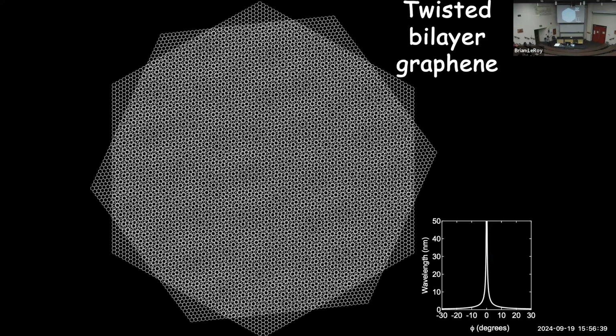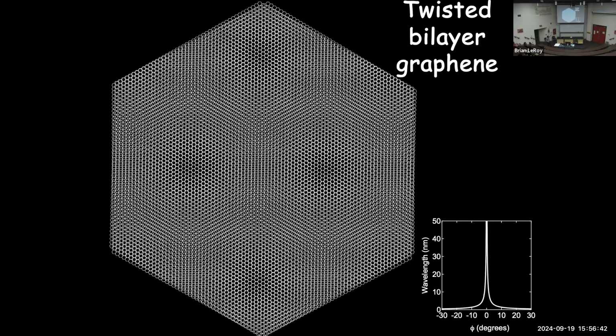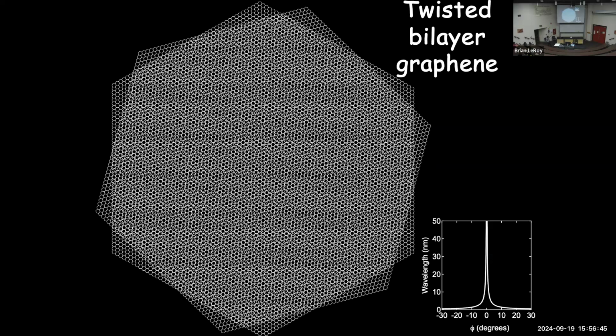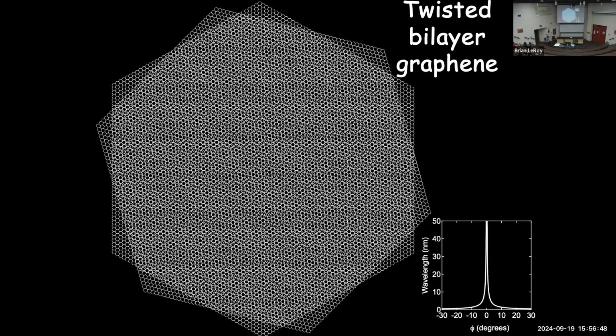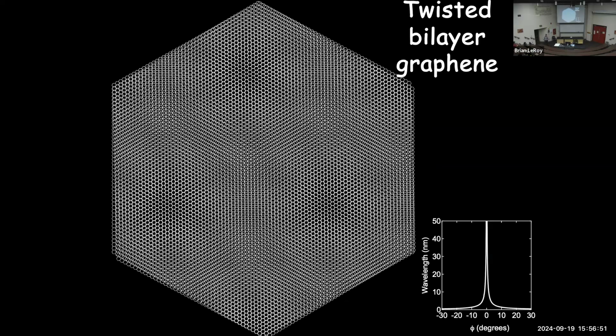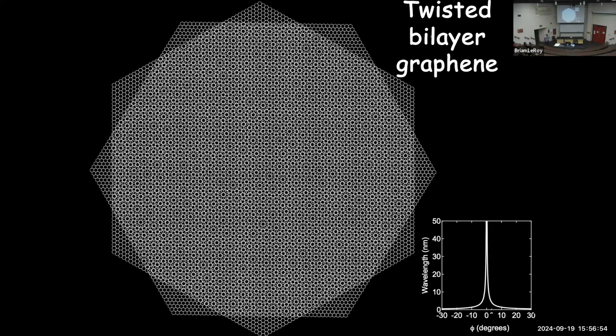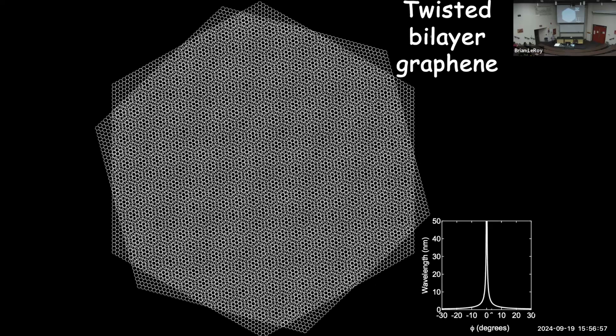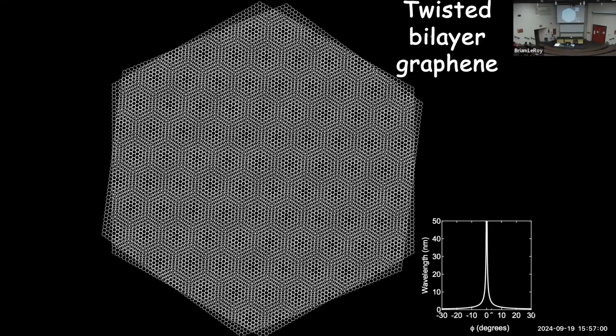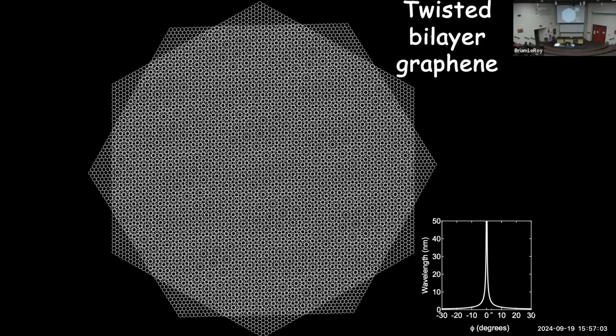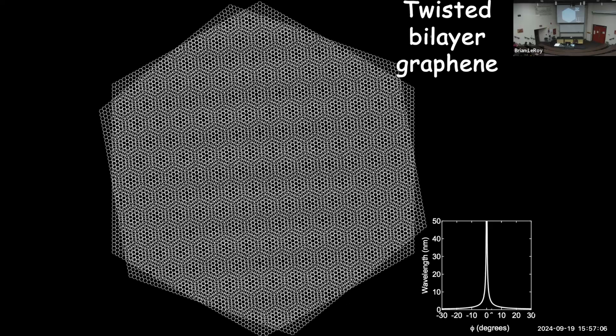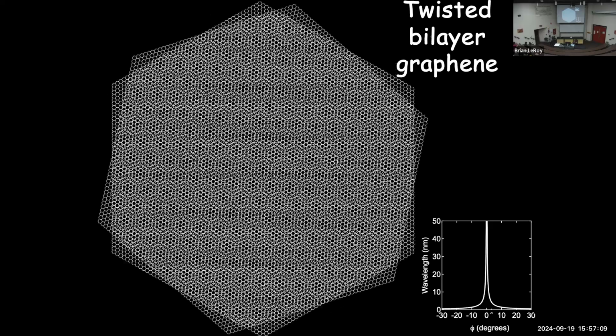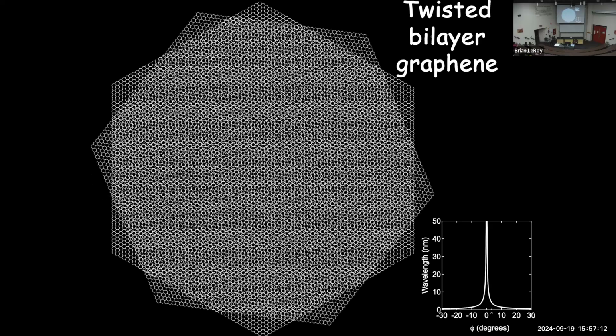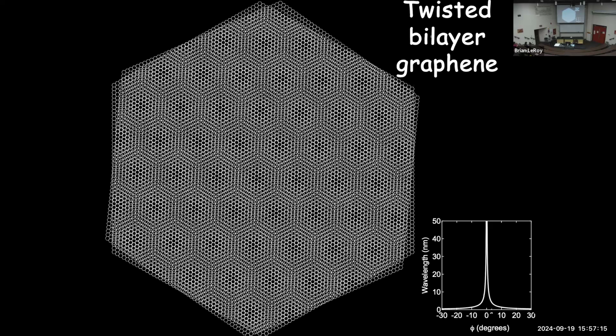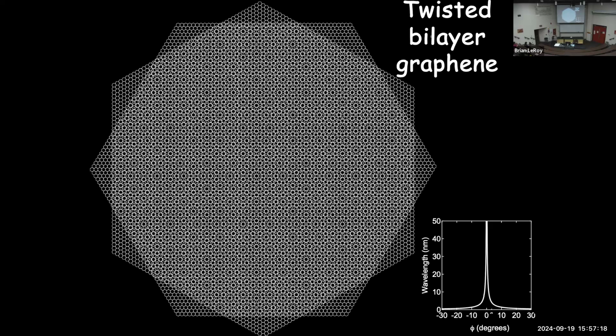So as I rotate these around, you see there's this moire pattern that forms, went out and back in. Here, it's going to go out again here in a second, as this comes out and goes in. And so there's a new periodic structure that's formed in this heterostructure that's not present in the individual layers. Right? The individual layers have an atomic sort of structure of a few angstroms for their periodicity. Here, by tuning this, we can change the periodicity of this structure as a function of twist angle, everything from the very small, when they're 30 degrees out of rotation, to when you go right near 0, you can get extremely long periodicity structures. And so this is obviously just a PowerPoint animation.